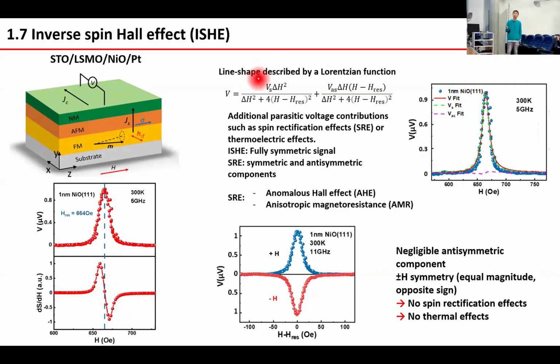And the inverse spin Hall effect voltage line shape can be described by the Lorentz function below. However, there are also additional voltage contributions, such as the spin rectification effect or the thermal effect. So it's important for us to separate these effects. What we do is fit the inverse spin Hall effect voltage, where the inverse spin Hall effect is a fully symmetric signal, while the spin rectification effect has symmetric and anti-symmetric components. In our case, the data show that the inverse spin Hall effect is a fully symmetric curve with a negligible anti-symmetric component, indicating almost no spin rectification effect. And also we reversed the magnetic field and measured the voltage, which is quite identical in amplitude, indicating there is no thermal effect as well.